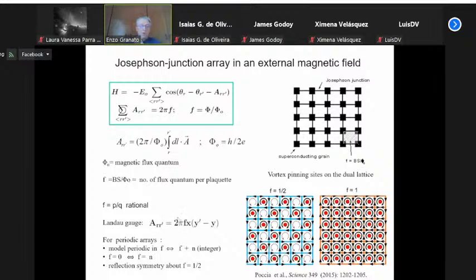So you can also show, using this relation here, that if f is an integer, then the system is exactly the same as if f is equal to 0. So there is a periodicity of 1. The model is periodic with period 1. And you can also show that there's a reflection symmetry around 1/2. So if f is slightly above 1/2, it's the same as if f is slightly below 1/2. Of course, this only works if the system you describe is perfectly periodic. If the system is not perfectly periodic, then this periodicity doesn't hold, but it still holds as an approximation.